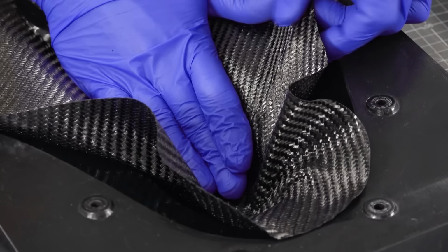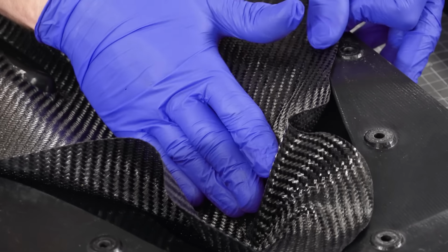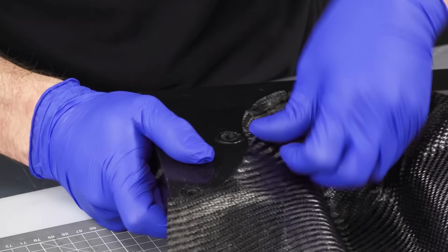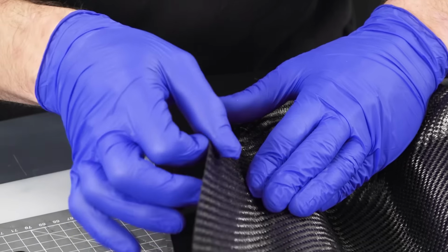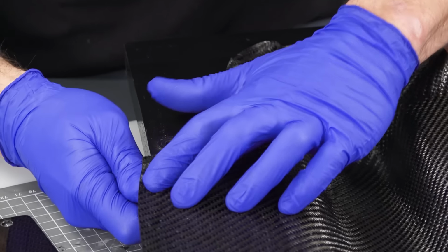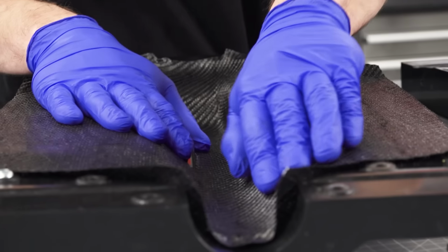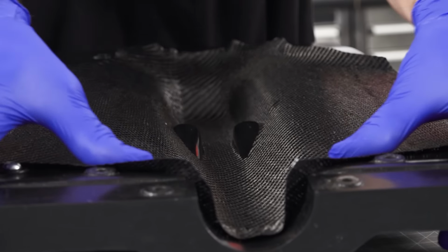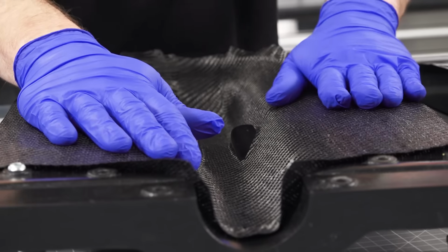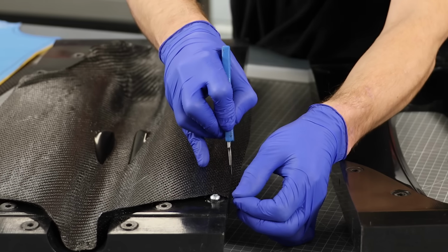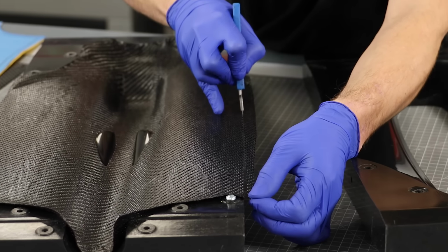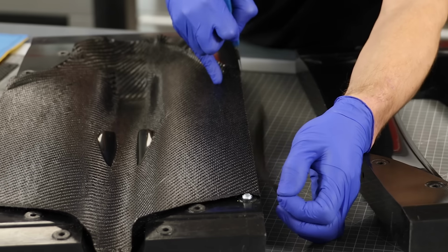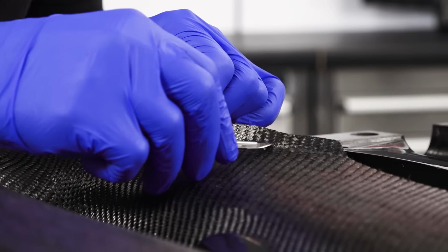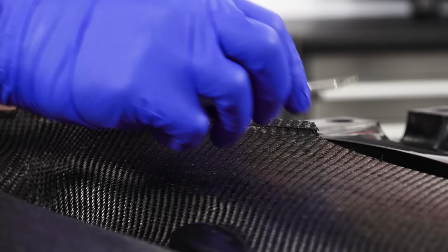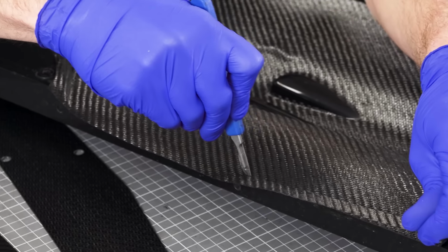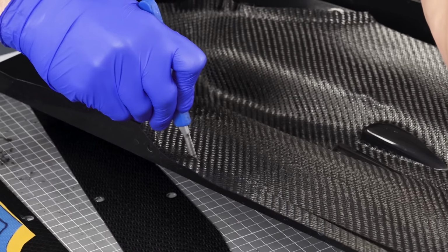As discussed, the lap strategy will see the surface plies trimmed perfectly to size and come together to form a neat butt joint at the parting line, with the second ply shortened on the lower half and then extended on the upper half. This creates the overlap that will join the halves together. So the first ply of the lower surface is laminated and then carefully trimmed back with a scalpel to meet the parting line. When you're doing this, be really careful to present a flat blade surface as to not scratch it, as otherwise you will find that your mould might not last for that many cycles.